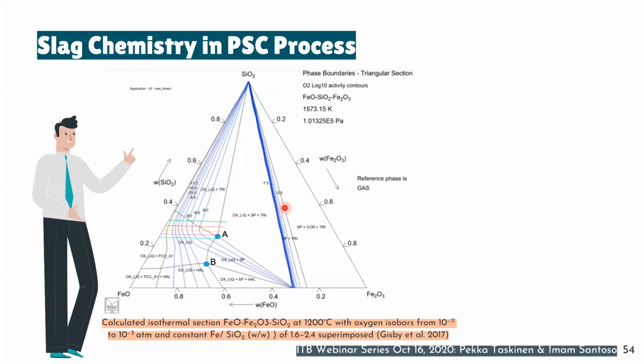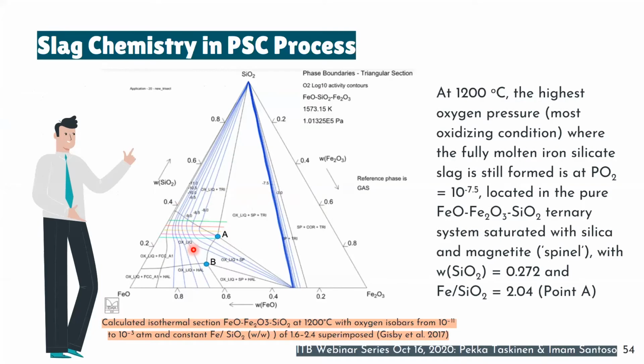For example, in here the oxygen pressure is 10 to the minus 3, it is very oxidizing, but on the left it is less oxidizing. When we want to produce good slag, the slag has to be liquid. And this is the liquid area of the slag. And the second thing is that we need a very oxidizing condition. Why? Because converting is an oxidizing process. So if the condition is very oxidizing, then I can remove a lot of iron. So the most oxidizing condition is point A. At point A, we still have liquid slag, and also the oxygen pressure is high.